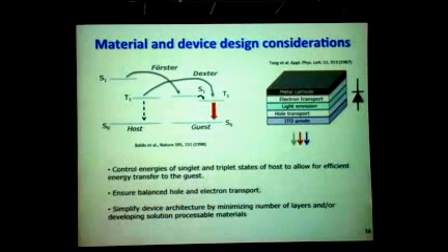They introduced organometallic electrophosphorescent dopants, where due to the presence of a very heavy element in these molecules, you have a strong intersystem crossing, and if you dope these materials into a matrix, you can actually harvest all the singlet states, which then turn into that mixed singlet-triplet state from which you can have emission, as well as harvesting of the triplet through some Dexter energy transfer. As a result, you can harvest 100% of the excited states, and make materials and devices that are very efficient.